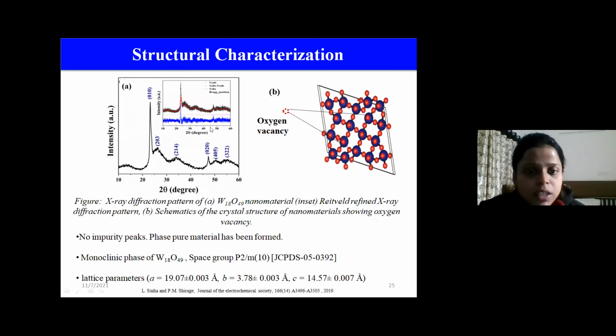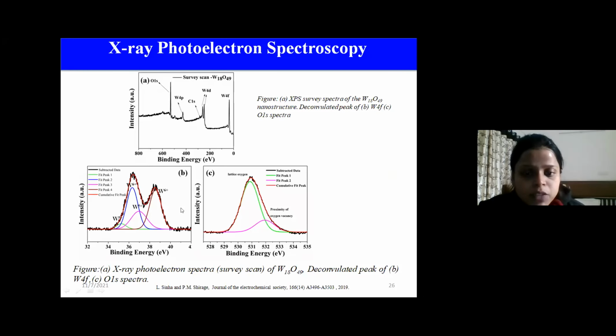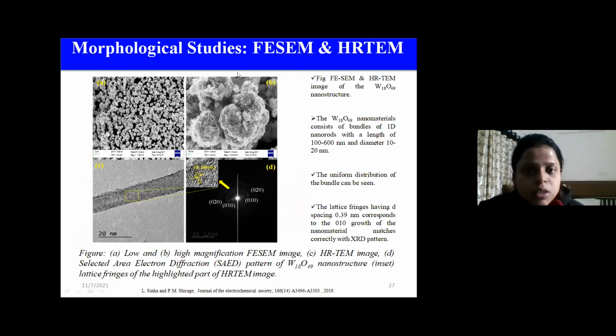So first we have conducted the structural characterization XRD, and we are seeing that the material is in its pure form. Now the XPS is for confirming the presence of oxygen vacancy, and from the oxygen deconvoluted peak, we can see that the material has an oxygen vacancy. So this is the morphological study of the W18O49 nanomaterial, and here we are seeing that bundles of these nanorods have been formed, and these are the HRTEM image, SAED pattern and lattice fringes, which confirm the single crystalline growth of the nanomaterial.